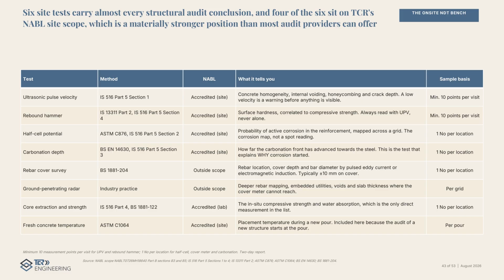6 site tests carry almost every structural audit conclusion, and 4 of the 6 sit on our NABL site scope. Ultrasonic pulse velocity for homogeneity and voiding. Rebound hammer for surface hardness, always read with pulse velocity and never alone. Half cell potential for a corrosion probability map across a grid rather than a spot reading. And carbonation depth, which is the test that explains why the corrosion started in the first place. All 4 accredited. The cover survey and ground penetrating radar sit outside accredited scope, and we mark them. Core extraction is accredited in the laboratory and is the only direct measurement in the list.